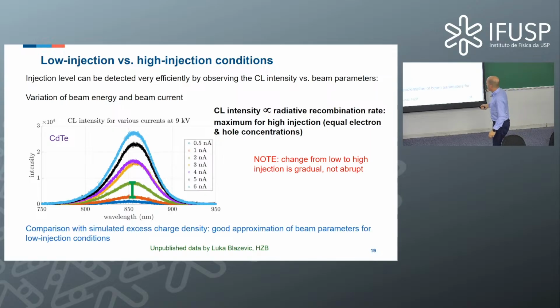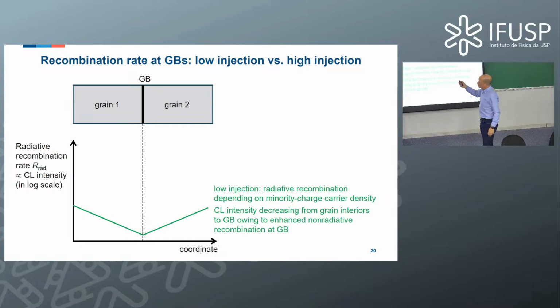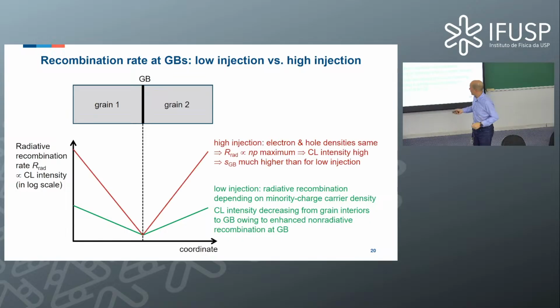And so what we can do is to estimate where we have to remain with the current in order to remain in low injection conditions. If you look now at what happens at the grain boundary, it is exactly a consequence of what I explained to you. As long as we are in low injection condition, we have in the grain interiors a certain level for the luminescence intensity, right? And then there's a decrease at the grain boundary because of higher Shockley-Read recombination at the position of the grain boundary. But if we go to high injection conditions, there is all of a sudden a very high luminescence intensity. And the decrease is much, much stronger.